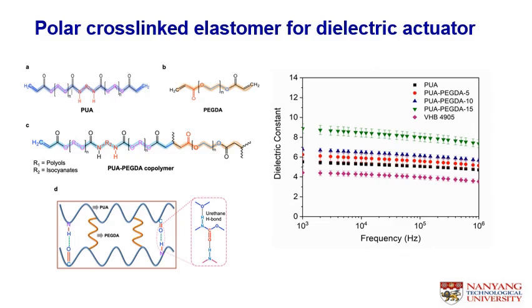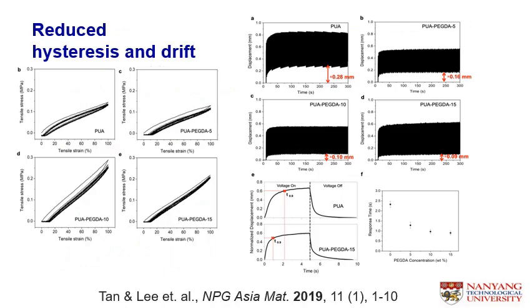Over here, we have added the polar crosslinker PEGDA into the PUA. As a result, the dielectric constant is enhanced as a function of the amount of polar crosslinker added. The mechanical stress-strain curve also shows a reduced hysteresis as a function of polar crosslinker addition. This leads to an actuator that has a minimum displacement of just 0.09 mm with 15 weight% of polar crosslinker addition, and the response time has also been improved.